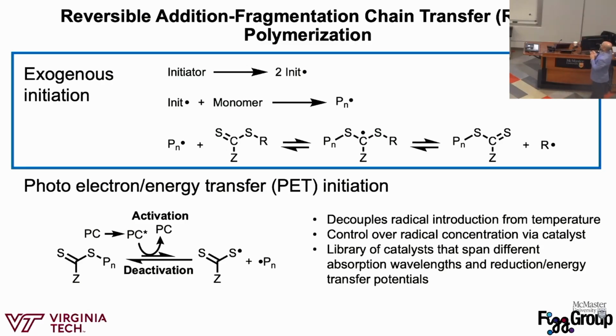The other idea is that you can really readily control radical concentration via the catalyst and the light intensity. So again, if you have a pretty high energy intermediate that can degrade with a pretty low concentration of radicals around, you can tune radical concentration pretty readily just by changing the photocatalyst, and it's a pretty direct input compared to some initiating systems.